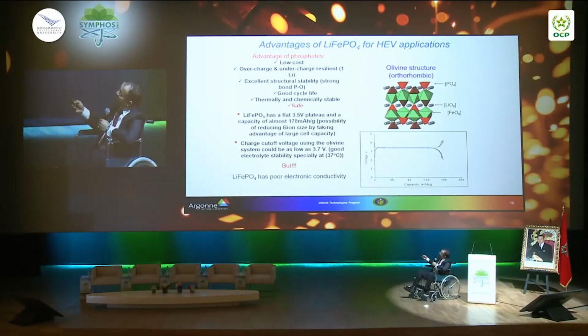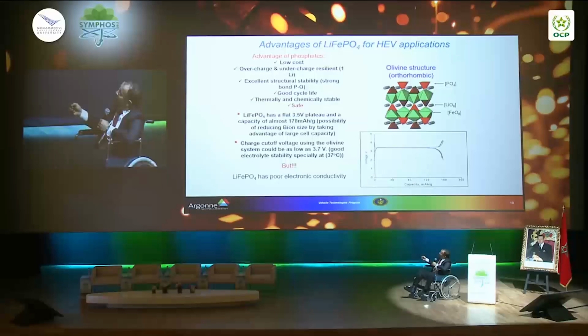It has a lower potential compared to the oxide, but not that low: 4 volt versus 3.5 volt. Capacity is fairly high, similar to the oxide. So the advantage here is, when you remove lithium, you charge iron from 2 to 3. And iron 3 is the most stable form of iron, so you don't have reactivity with the electrolyte. When you go higher in oxidation state, the reactivity goes up.